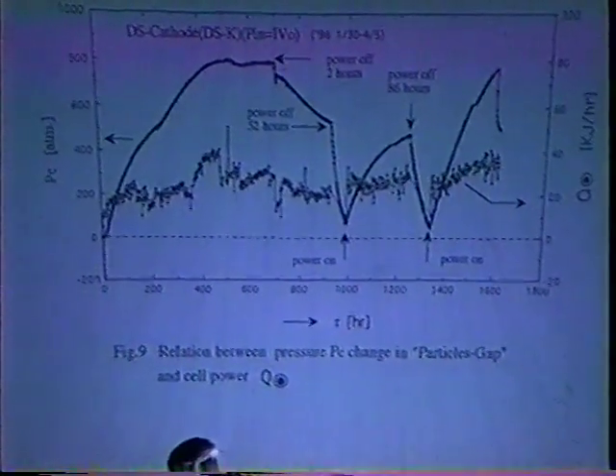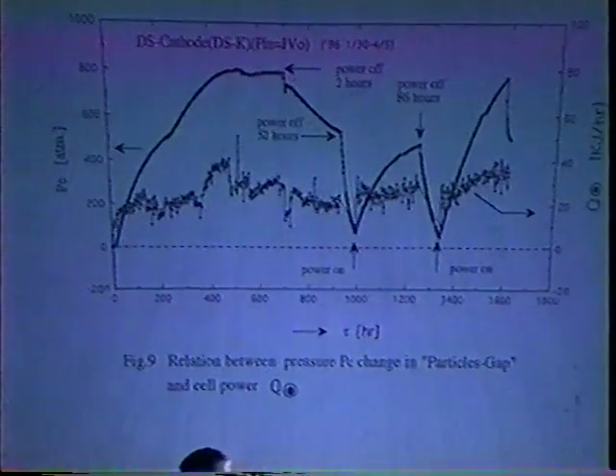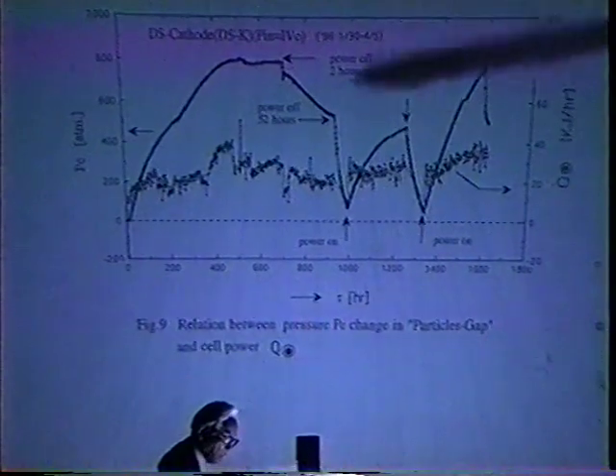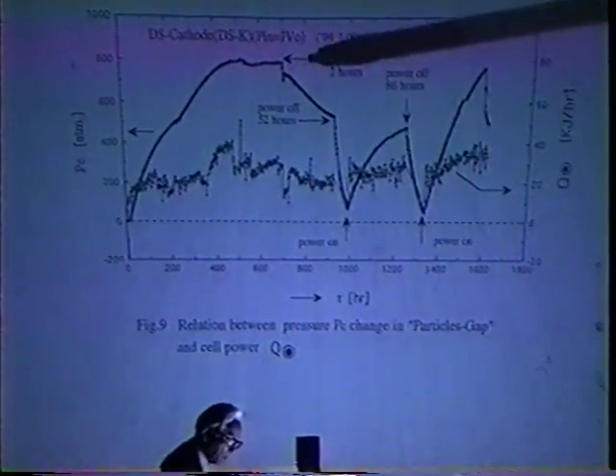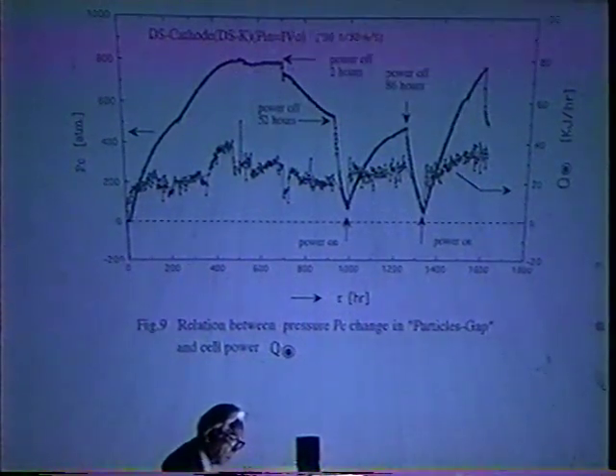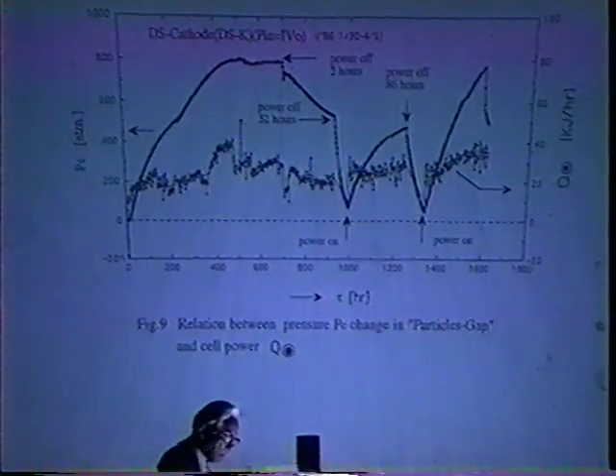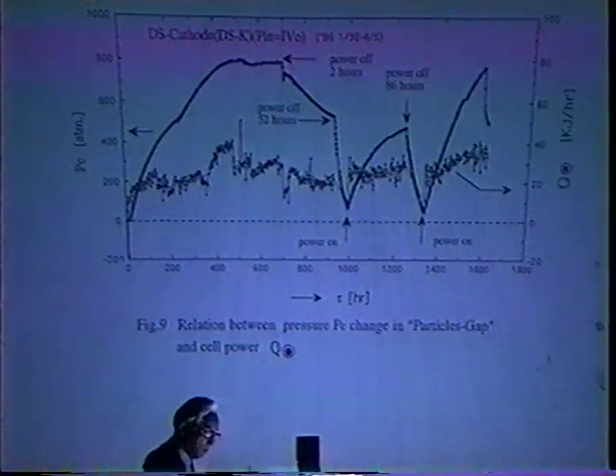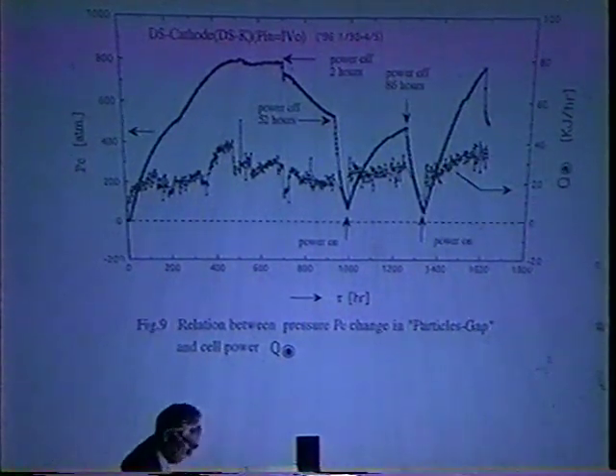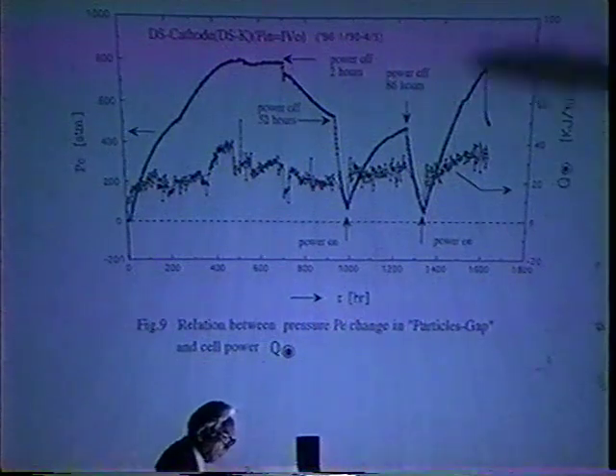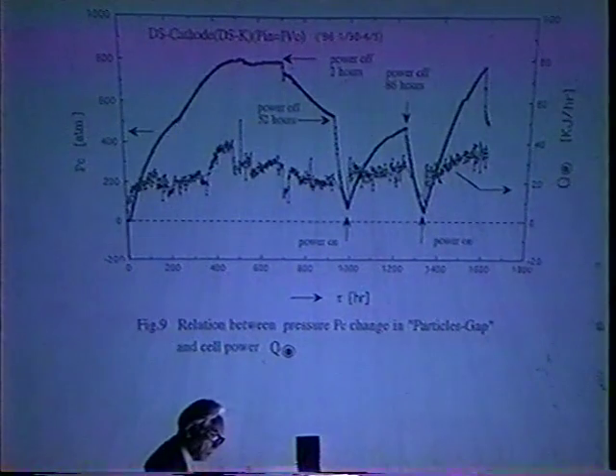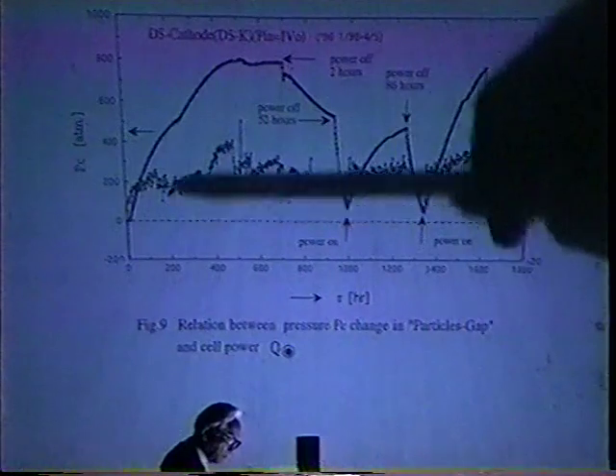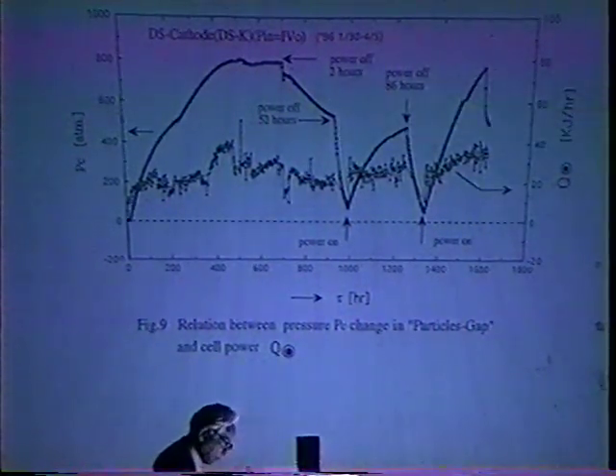This is the inner pressure. This is elapsed time. And this is the cell power, so-called excess energy. This is the pressure, and after a 2-hour stop with power off, the inside pressure suddenly decreases. Then, when switched on, it suddenly goes up. And this is the cell power, the excess energy, like this. And so it looks like it corresponds to the pressure.